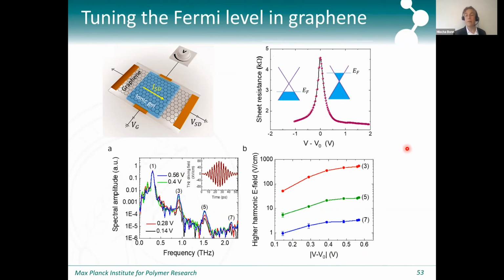So it works. You also see that it levels off because at some point the amount of electrons also starts limiting the nonlinearity. You can't heat up the electron bath so much if you have more carriers that you have to heat up. So there is a limitation to how far you can push this.